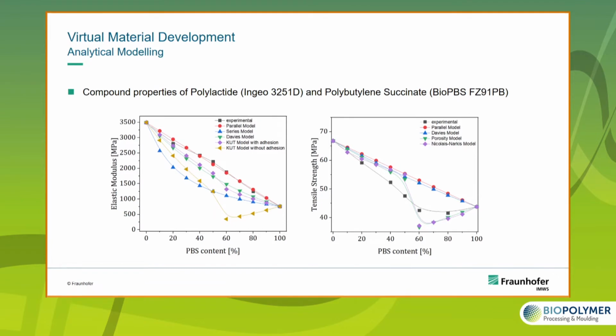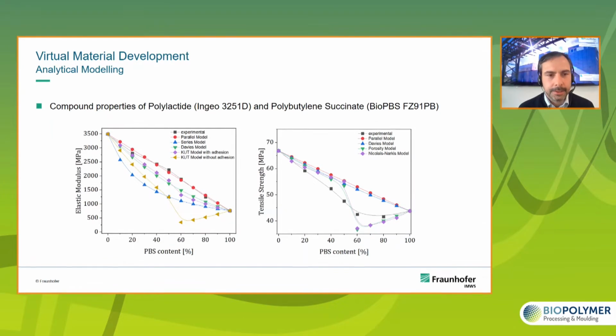On this slide, you can see our results on mathematical prediction of the stiffness and strength of a binary blend of polylactide and polybutylene succinate. And you can see here in the diagram on the left side that, first of all, the stiffness of the blend goes down with increasing PBS content, and this is very well predicted by the parallel model. On the right side, you can see that also the strength is decreasing with increasing PBS content. And here you can see that not the parallel model, but other models like the porosity model or the Nicolais-Narkis model are much better to predict the slope of the experimental curve. This is due to the quite complex microstructure of this binary blend with increasing PBS content.